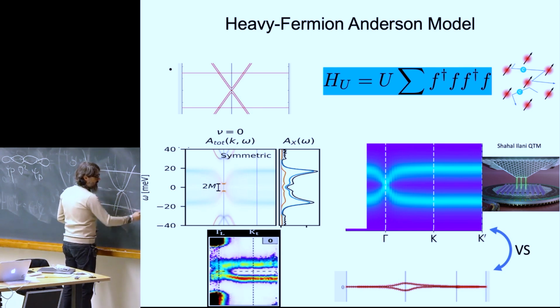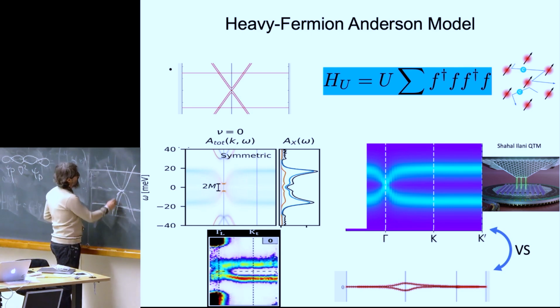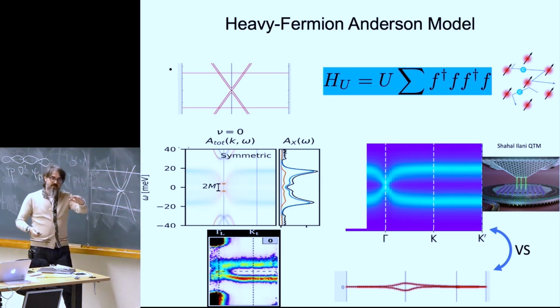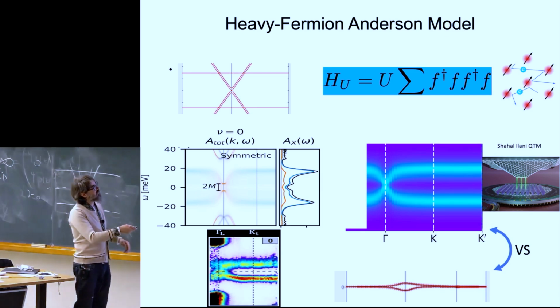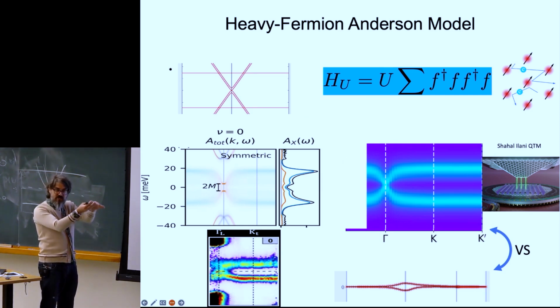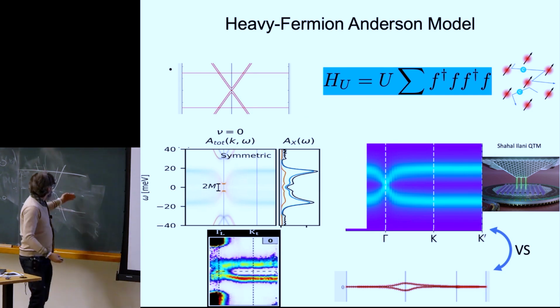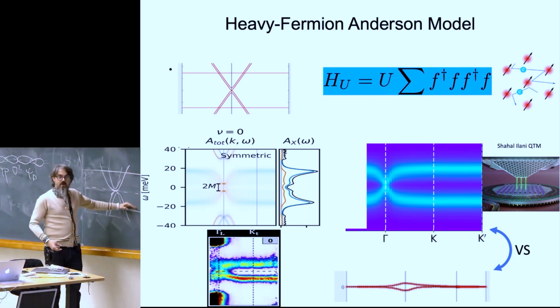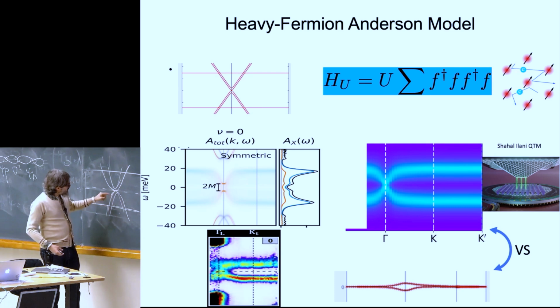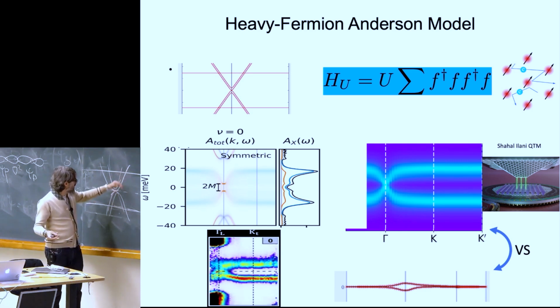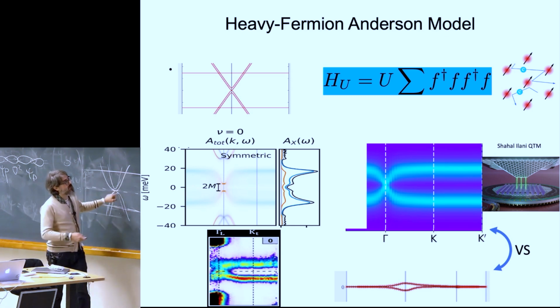So these are called Mott-Hubbard bands, obviously condensed matter physicists know they're called Mott-Hubbard bands. It's just that an interacting system with a flat band at the Fermi level doesn't like to sit at the Fermi level because it can lower its energy by moving the electrons down and up. So I move the F electrons here and here. These are now Hubbard bands. And you can notice that because you have topology, unlike in a Mott insulator where this would become an insulator, you cannot gap this. This is a Mott kind of semi-metal. So you have Hubbard bands, but you have a semi-metal which stays topological.